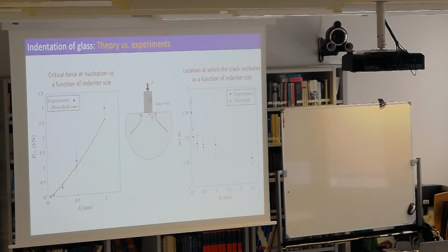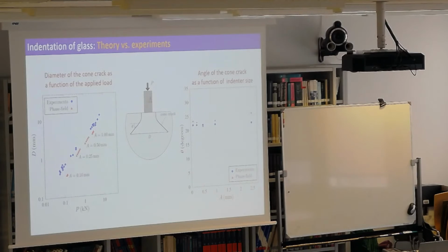So this is the numerical comparison with the distance at which you have the ring crack nucleated. And then you can compare things that have to do with propagation, with the cone crack. This is the diameter as a function of the force. You apply displacements, but you can measure the force. And this is the angle, which experimentally was, what was it, 22? With the phase field, you get something comparable, right? So, all right. Once you nucleate, Griffith takes over, but you need to nucleate. In this problem, you nucleate because of what happens around shear.